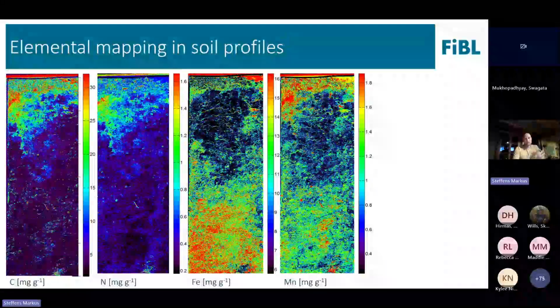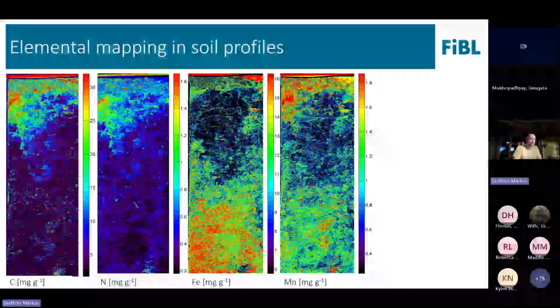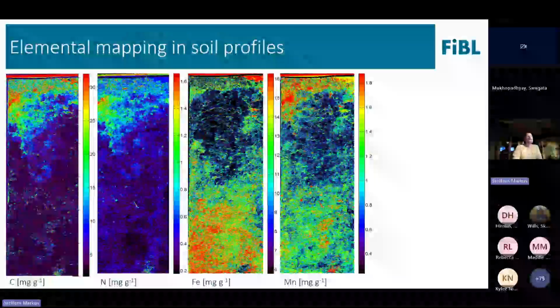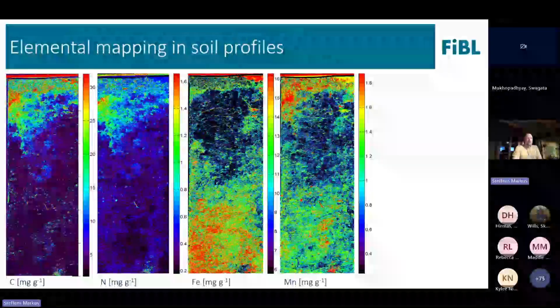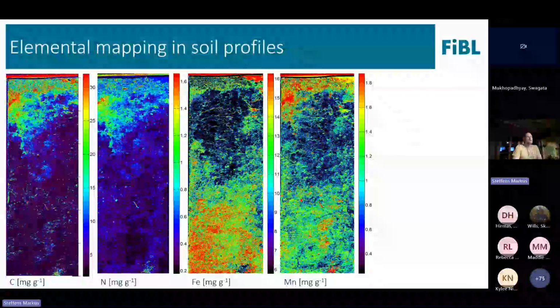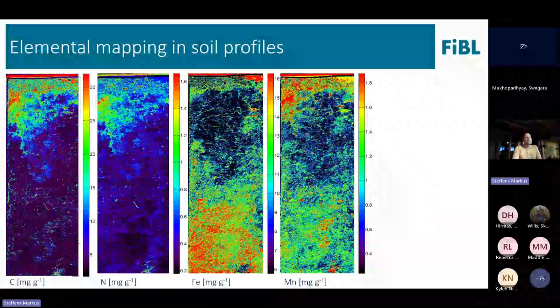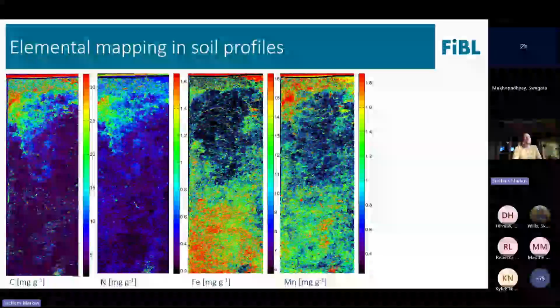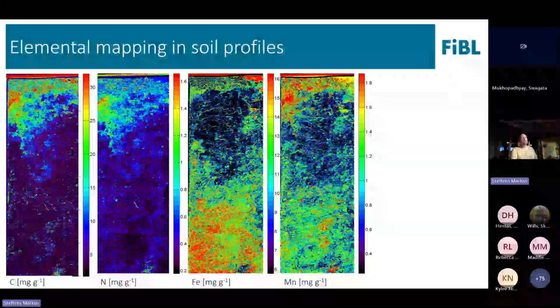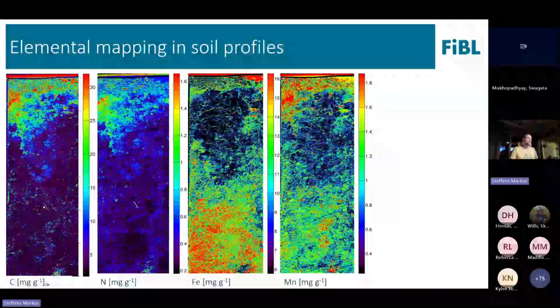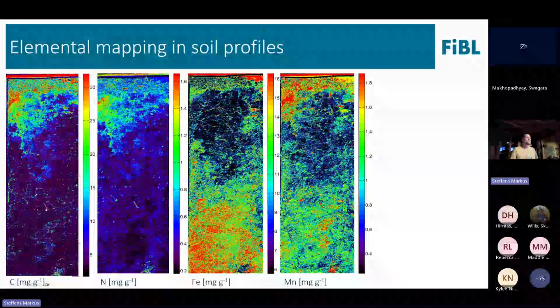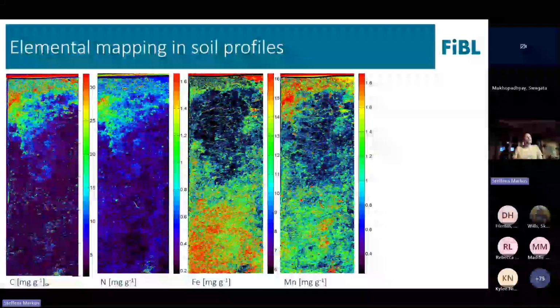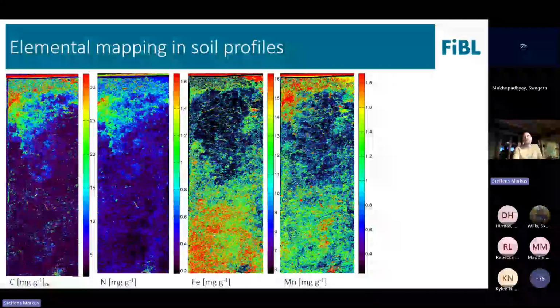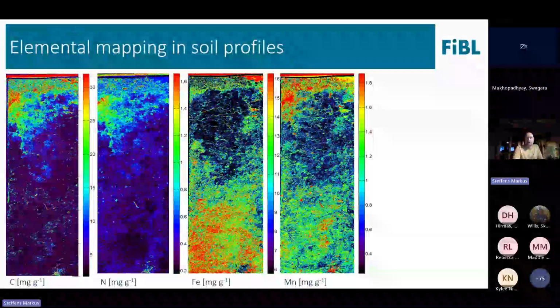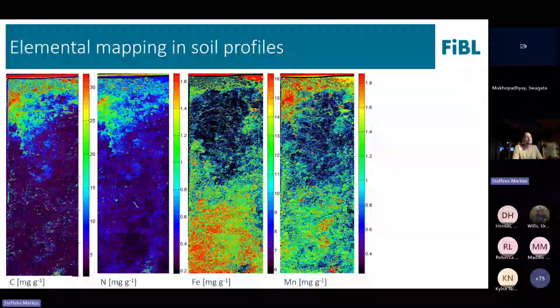Of course, this is also the very first try. And in the end, there's, of course, potential for improving, but I think it's quite a good proof that we can do elemental mapping on continuous soil profiles with a very high spatial resolution. And you can see, for example, this feature here is a root that we identified, or you see also this separation of the reducing and oxidizing parts of the B horizons.